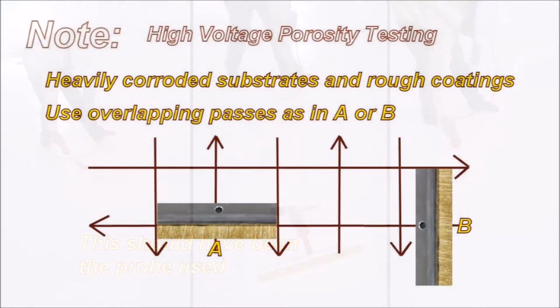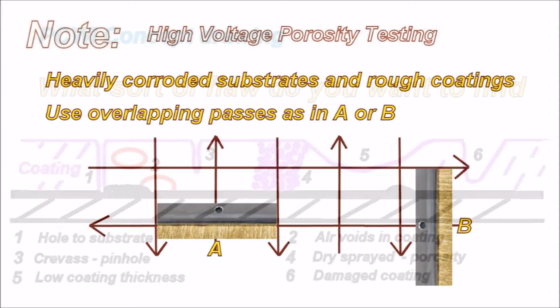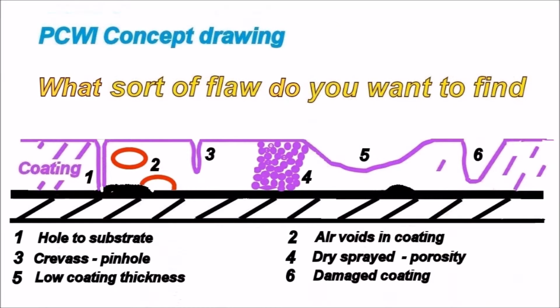Heavily corroded substrates and rough coatings: use overlapping passes as in A and B. This area of porosity that's shown as number 4 is a difficult area to find, a very difficult area to find. And you need enough voltage to virtually break through that to find it, if you're relying on the voltage to find it and not on a visual inspection. Number 5 is just a low area.